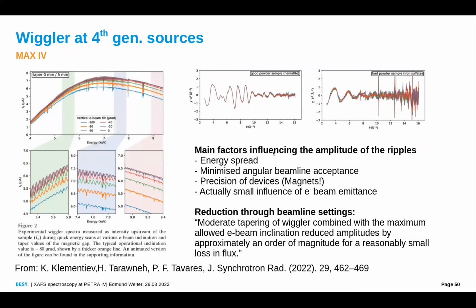For perfectly homogeneous samples, these oscillations, both in intensity and the spatial oscillations, are not important at all. But for real samples, and especially for bad samples, this becomes important. As you can see, this is a bad powder sample measured under different conditions with more or less smoothing of the wiggler spectrum. And you see that the spectra get worse the higher these amplitudes are.